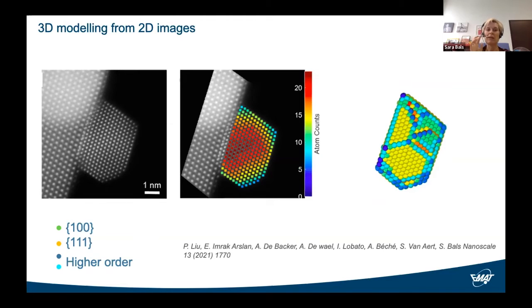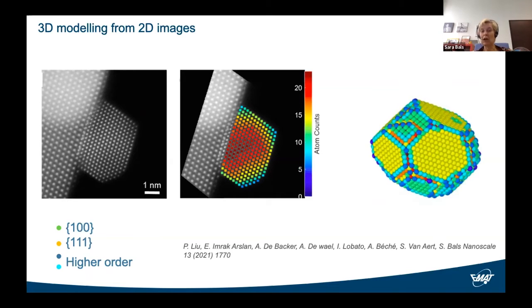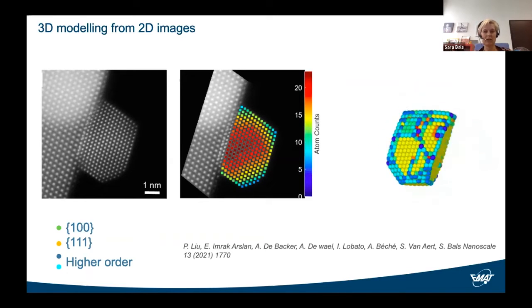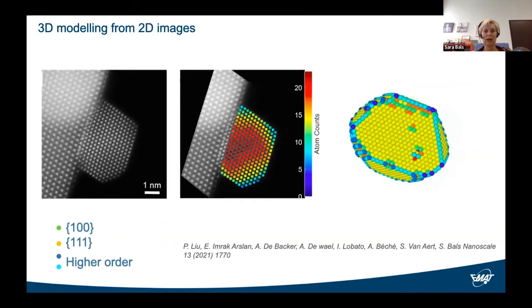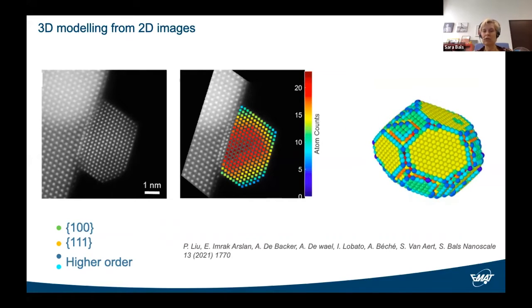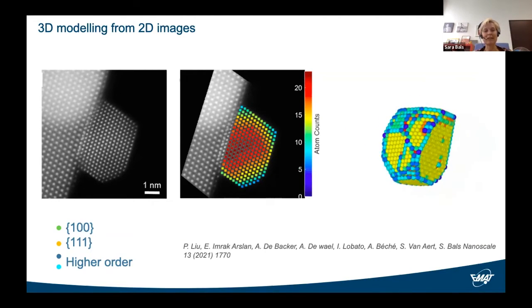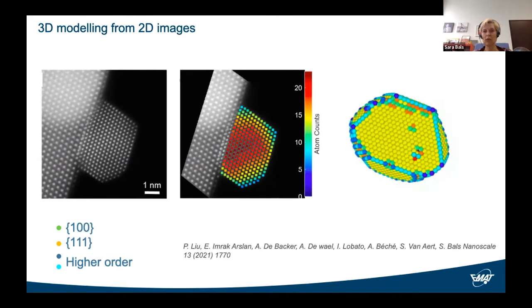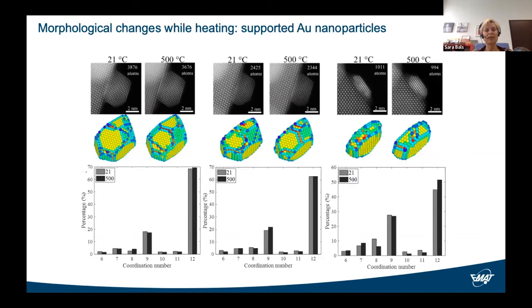Then we use these results as an input for molecular dynamic simulations. And then we can come up with a 3-dimensional model based on our 2-dimensional image. You can see that we are able to determine the type of crystallographic facets. And so this is the approach that we have used to understand transformations for the supported gold nanoparticles. And we made a comparison between room temperature and 500 degrees Celsius.